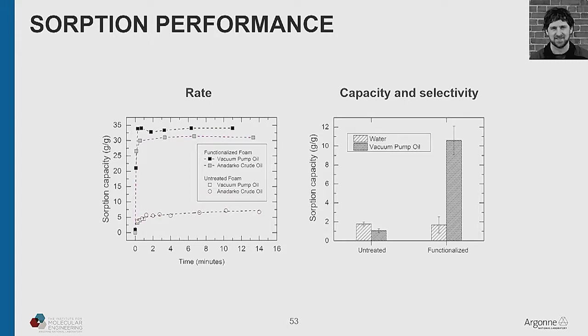So we've done other sponges that had larger porosity, and they can go higher. So we've gotten up to 90, for example, by doing it that way. In terms of selectivity, you can see the untreated polyurethane actually takes up more water than oil, and then it becomes highly oleophilic after the treatment.